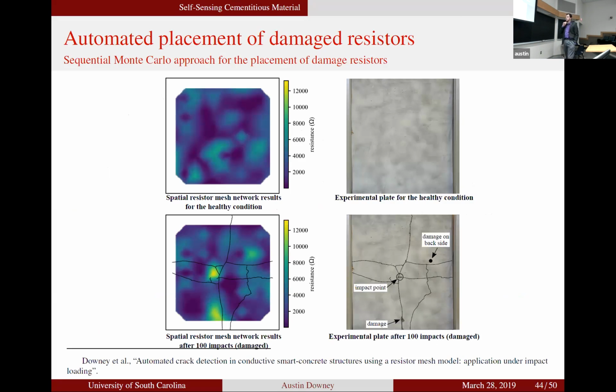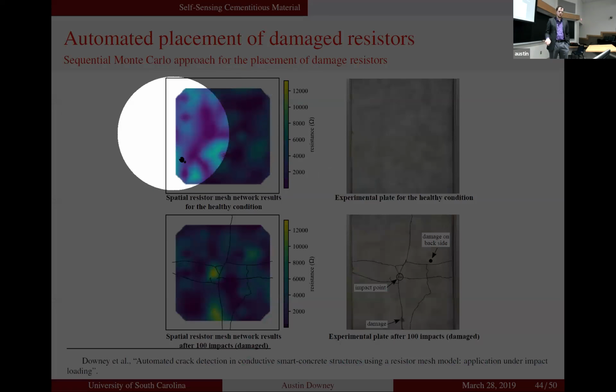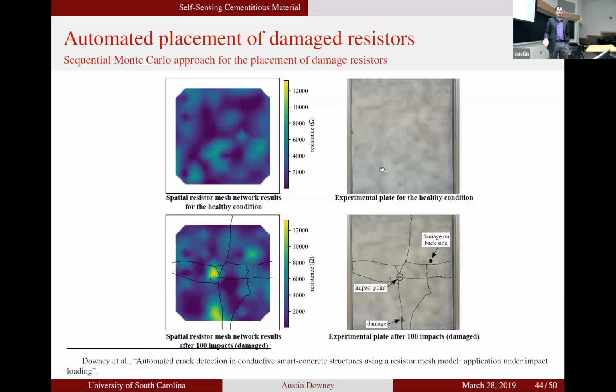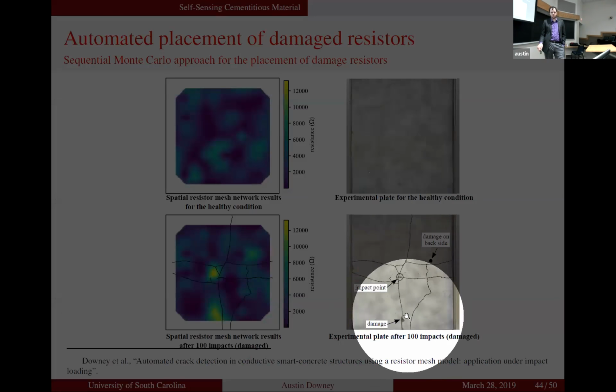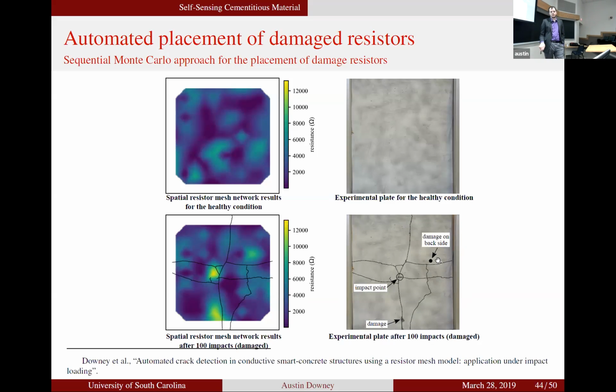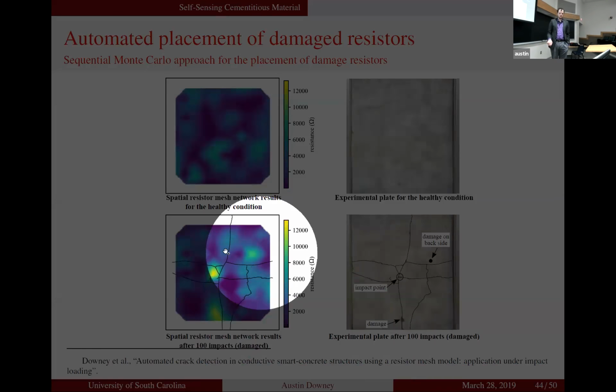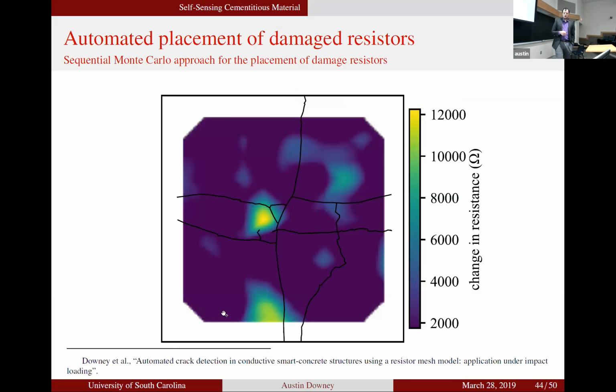So here we can see the pristine case of our plate. This is what our algorithm gives us in change in resistivity. And then after we impact it, we have 3 spots on the plate where actually we lost a little bit of concrete. And so we lost conductivity here, here, and then on the back, right? And the benefit of this method is it doesn't matter if it's on the front or the back, it can pick this up. And we were able to find kind of these 3 losses of material. If we subtract one from the other, we get a much clearer look, right?